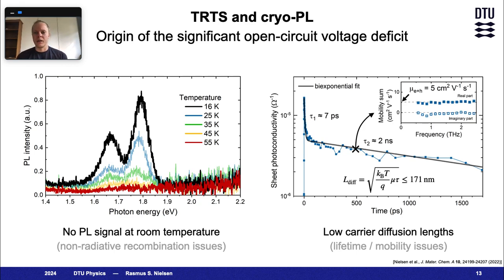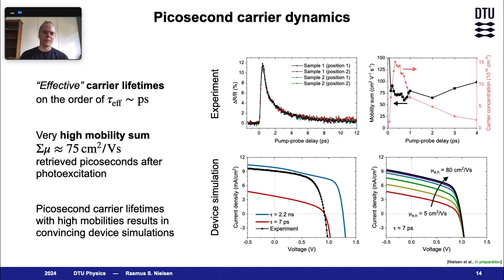We have also carried out time-resolved terahertz spectroscopy to analyze the carrier diffusion length, and at a first glance, it looks as if we have both problems with the carrier lifetime and the mobility. However, if we for a second assume that the effective carrier lifetime is reflected by the rapid initial decay in a transient, the mobility sum is actually quite impressive.